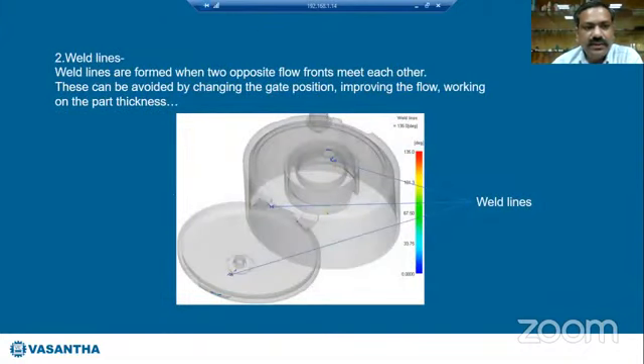And the second issue is about weld lines. This is where 2 opposite flow fronts meet each other. There we would see some sort of line or mark on the product. This also can be improved or avoided by changing the gate positions, improving the flow pattern, and sometimes by increasing the wall thickness or working on the wall thickness parameters, we can avoid these weld lines.